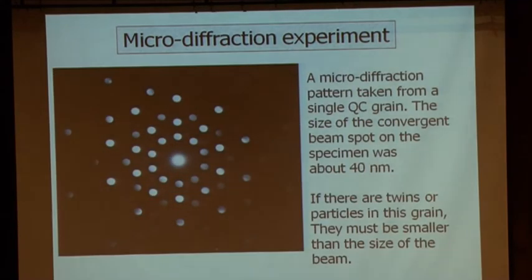Okay, the last experiments that I did that day was micro diffraction pattern or convergent beam diffraction pattern, or convergent beam electron diffraction, CBED it's called nowadays, and it contains a lot of information, a wonderful tool. But here I just use it to get a diffraction pattern, and what you do here is that when you converge your beam onto a small spot, then you can try and find a single twin, couldn't find any. Wherever I moved, the diffraction pattern appeared.